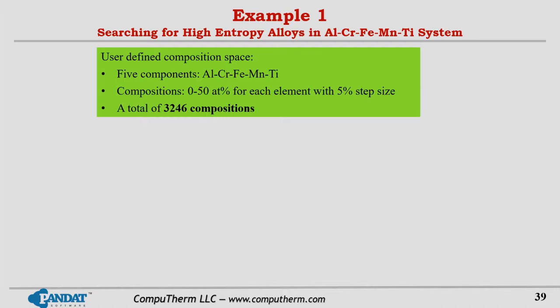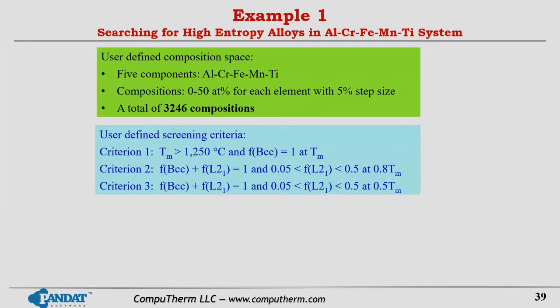It is a five-component system, and each component's composition varies from 0 to 50%, with a 5% step size for each element. The total number of compositions defined this way is 3,246 compositions. We perform high throughput calculation for all the compositions.